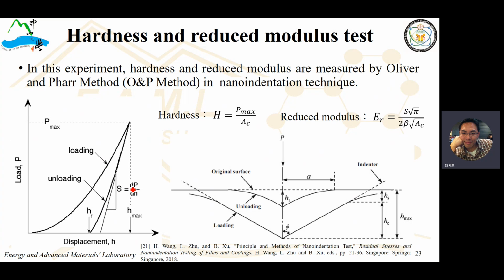And then we use nanoindentation to figure out its surface mechanical property. Okay, except for the anti-corrosion and anti-fouling, we have to realize whether the surface is relatively strong. Of course, it might not be stronger than some metals or alloys. However, we have to realize whether it's strong enough. Okay, that's why we use nanoindentation. That means we have indentation tips, diamond pyramid tips, to indent the surface of the polysilazane pre-ceramic precursor after curing, after pyrolysis or curing. And from its load and displacement curve, we can figure out whether this surface is strong enough or not.